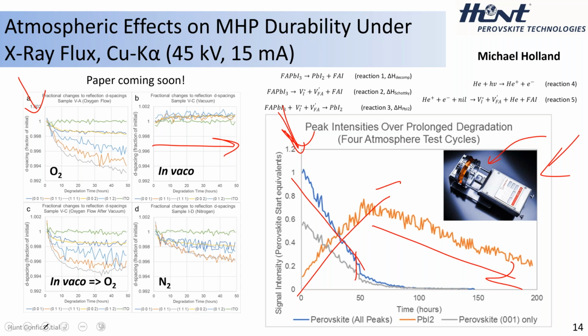In fact, there's actually a volume increase. We think that's important. I won't get into those details today, but we think that's actually important and relates to the defect structure. Now, what happens if you take the sample and heat it under vacuum conditions, and then expose it to oxygen? Is there something we're doing to achieve a unit cell volume increase that's irreversible? Are we changing the material in a fundamental way?